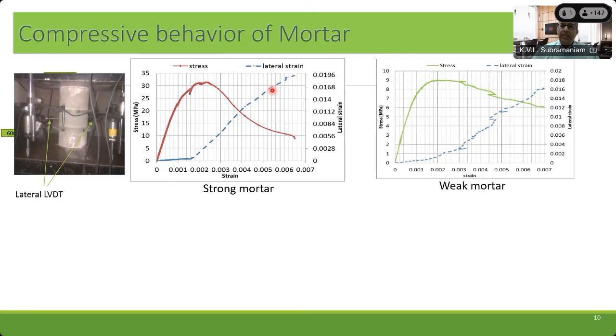Now, if you look at a weak mortar, so this is a mortar that we made, which actually was not as cement rich. So this is a weaker mortar. Its strength was lower. You can see the stress strain response here in the green line. And this is the lateral expansion. You can see that even this mortar actually has a good amount of expansion that is taking place as the material is failing. The actual failure of the material, if you look at the strong mortar, happens somewhere here. This is where the material completely crushes. And if you look at the kind of expansion that is produced before the material fails completely, it's a good amount of expansion that has taken place.